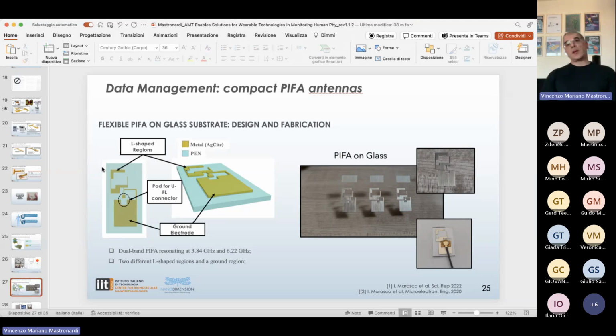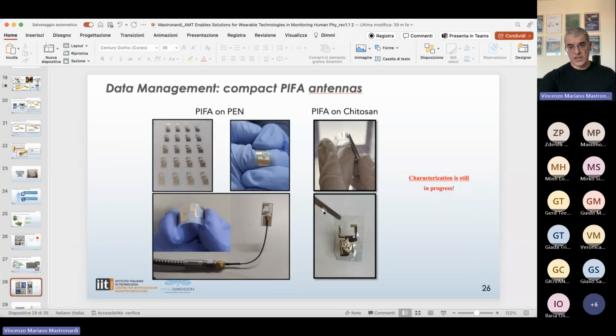We also developed a second kind of compact antenna, that is the PIFA antenna, that has a planar design, so it's easier to fabricate. We tried to fabricate these PIFA antennas on different substrates, starting from the glass, as you can see from these pictures, but also moving on flexible substrates, especially on polyethylene naphthalate and on chitosan substrate. It is a very interesting and performing material. But the characterization in terms of radiation patterns of this antenna is still in progress.